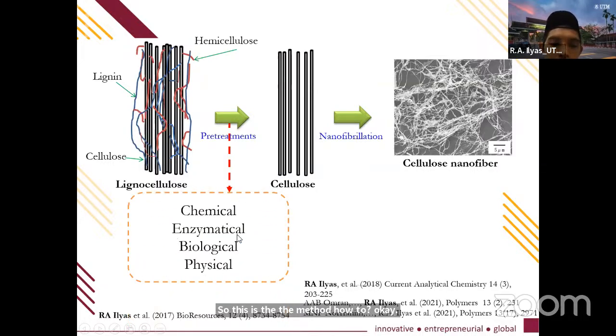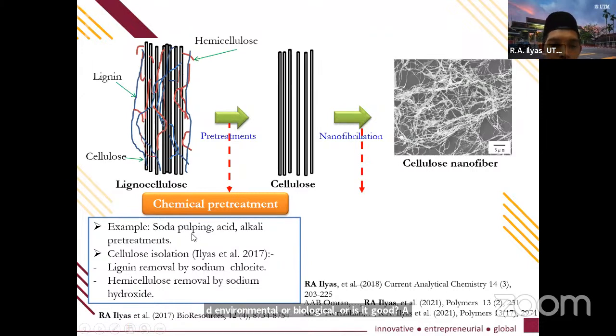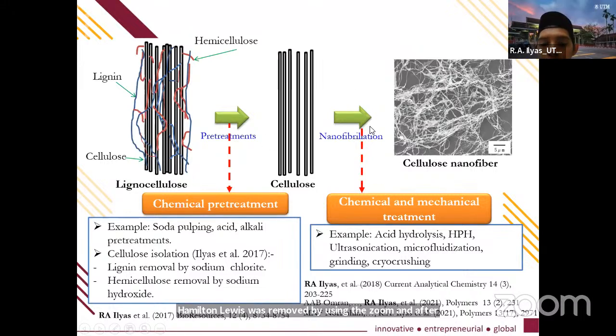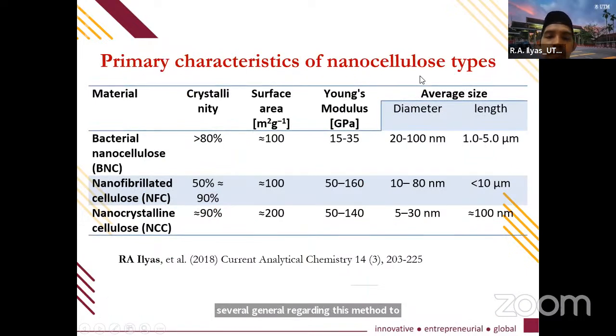We can use a pretreatment, using a chemical, enzymatic, biological or physical method. For example, we can use soda pulping, acid and alkali pretreatment, and then cellulose isolation. Lignin was removed by using sodium chlorite, and the hemicellulose was removed by using sodium hydroxide. After that, we get cellulose. We can extract the nanocellulose using chemical and mechanical treatment. One example is acid hydrolysis, which is an acid treatment. For mechanical treatment, we can use a high-pressure homogenizer, ultrasonification, microfluidization, grinding, and cryocrushing. I published several journal papers regarding these methods to extract the cellulose. Next is the primary characteristic of the nanocellulose.